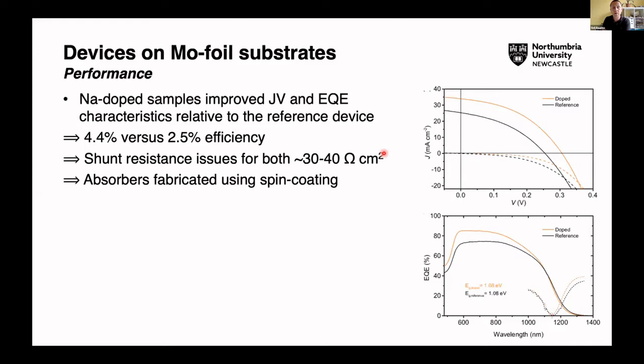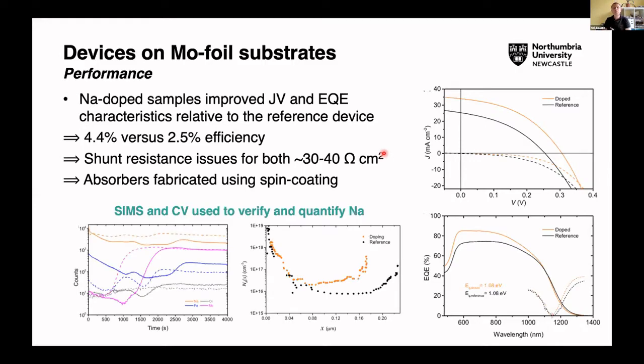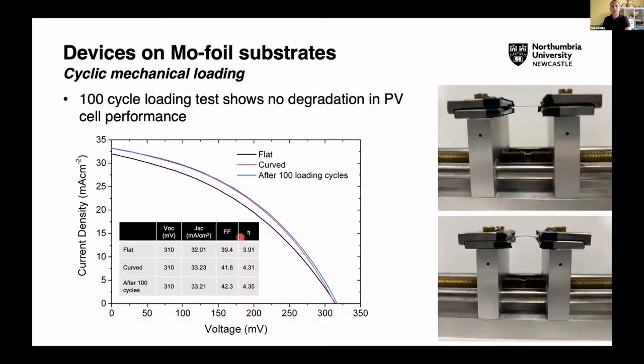The EQE shows the effect of the doping, and if we want to quantify the doping, we used SIMS first of all to qualitatively check where the dopants are. So there you have the orange dashed line here. This is the sodium doped sample, and it tells you where your sodium is in the device, and we've got overall higher levels for the doped device, as you'd expect. And then when you do the CV to look at the profile of the acceptors, you can see we can to some extent quantify this for the doped device. So that was really a simple, manufacturing compatible technique that we used to introduce dopants.